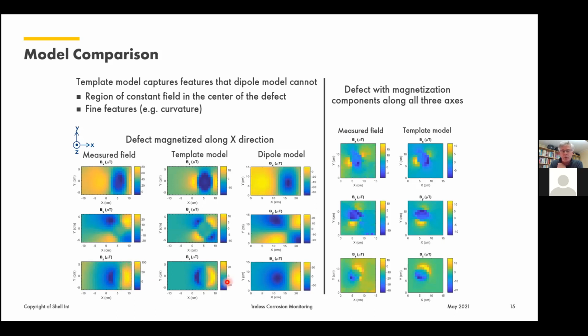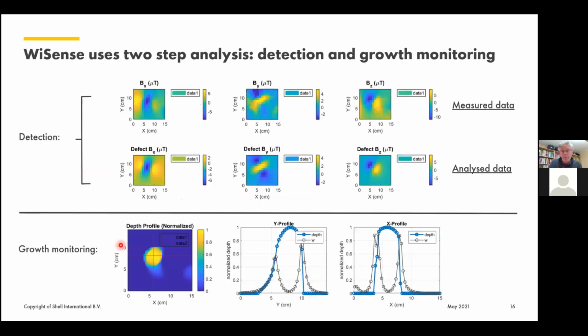If you would use a simple point dipole model, you can see that there is a much larger discrepancy. And this illustrates that using a template that represents a defect of a certain length, a certain width, and a certain orientation in the magnetic field makes a good match with what you actually measure on a defect. Now, highly technical, I want to leave this for a while.